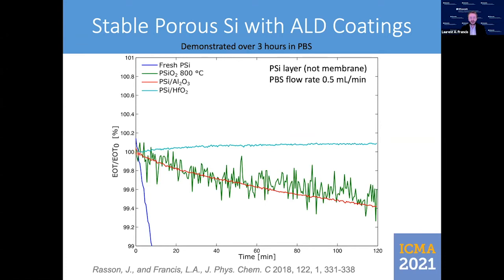Then when we have an oxidation, simply we have the green curve, which is here. So we can stand for longer in the saline solution, but the noise is higher, as you can see. Then when we have the aluminum coating, we have the red curve. And in that case, we see that we have a stable membrane over time and a better resolution due